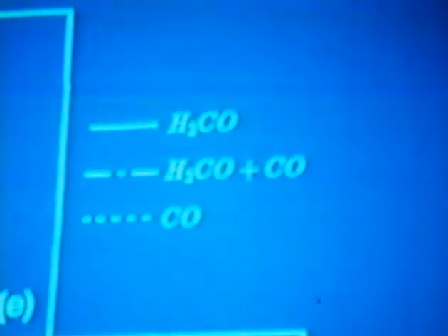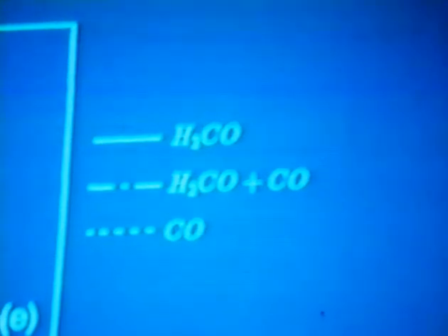Now, what I will show next is I'll gradually put this figure together. I'm going to show results of 5 catalysts, same 5 that we looked at previously for methanol oxidation. And we'll show results of formaldehyde oxidation. But in each frame here, for each catalyst, what I will show will be results of 3 separate experiments. The first involves just the oxidation of formaldehyde, given by the solid curve. The second is the conversion of formaldehyde in a stream that contains both formaldehyde and CO. And thirdly, just for comparison purposes, we show just the conversion of carbon monoxide in a feed that contains only CO and oxygen.